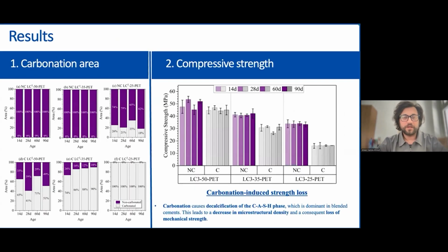Now let's go one step further into quantifying this carbonation depth. What we did was we took these cross-sectional areas and tried to measure quantitatively how much of the area is carbonated and how much remains non-carbonated. And here you see, for example, the results of LC350, which was non-carbonated, just hydrated. And of course, here you see the whole cross-section is non-carbonated, shown by these purple bars. Also LC335, because it was non-carbonated, shows the complete area is non-carbonated. But what's interesting is this non-carbonated LC325 matrix. Although we did not carbonate it intentionally, after taking it out from the fog chamber and before testing it, the time it was sitting in the lab environment, it started to naturally carbonate. And you see here the percentage areas of how much it was carbonated naturally.